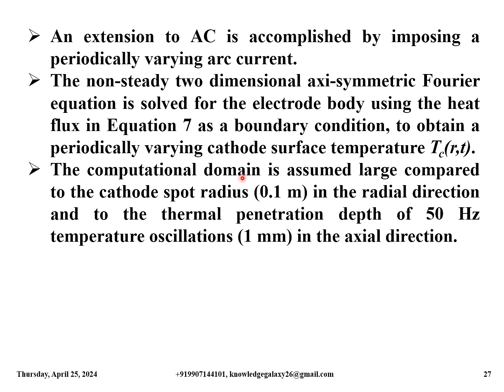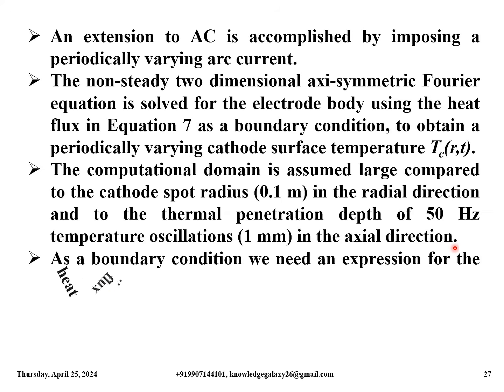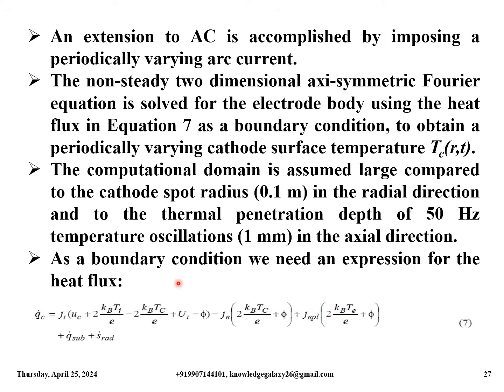The computational domain is assumed large compared to the cathode spot radius, that is 0.1 meter in the radial direction, and to the thermal penetration depth of 50 Hz temperature oscillations, that is 1 mm in the axial direction. As a boundary condition, we need an expression for the heat flux. So this is the equation number 7, which is the expression for the heat flux.